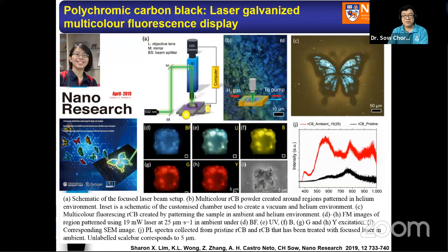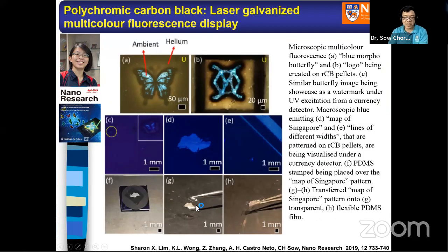So the idea is if you have a trace element of zinc, calcium, silicon embedded in it, you can generate oxide form, but what happens is carbon is in abundance in this matrix system. You can incorporate carbon atom into the mid-gap state. So you create all kinds of fluorescence level. You can tune its color, create beautiful butterfly fluorescence pattern just by a nice control of the laser beam. This is work done by Sharon on the cover of Nano Research. So it's small scale. We are trying to scale it up. It can go up to a few millimeter size.